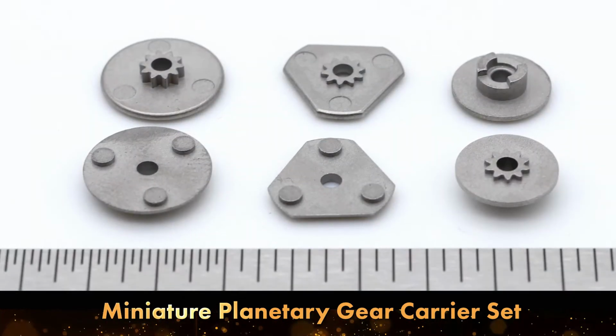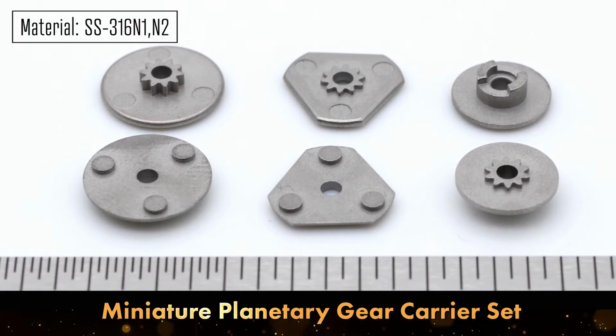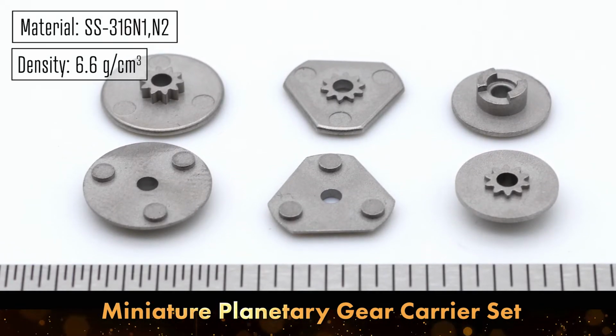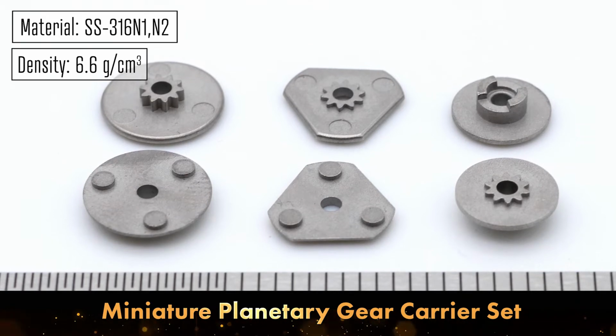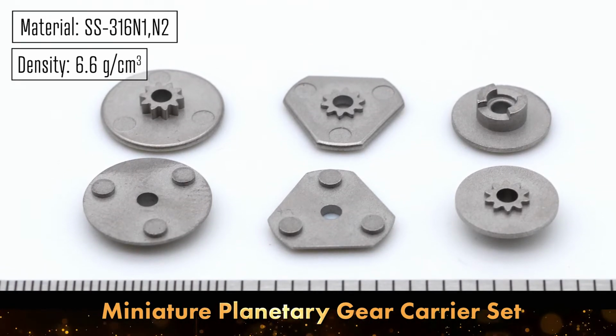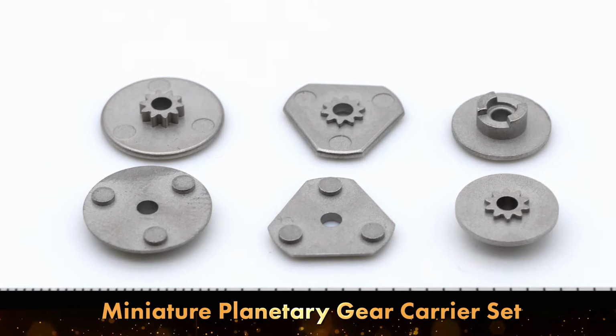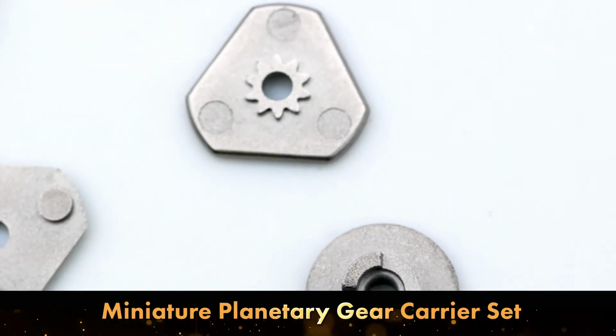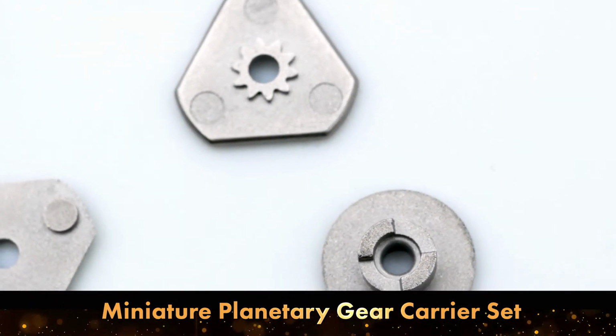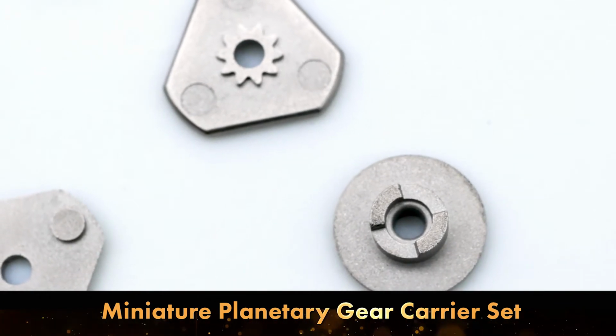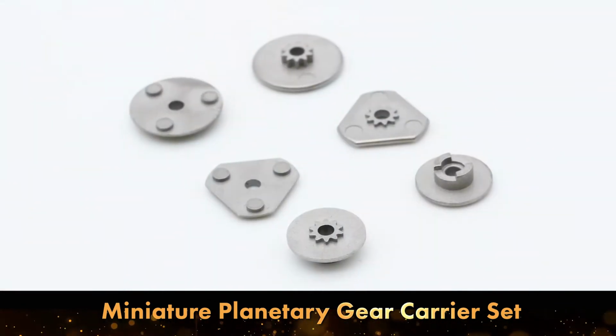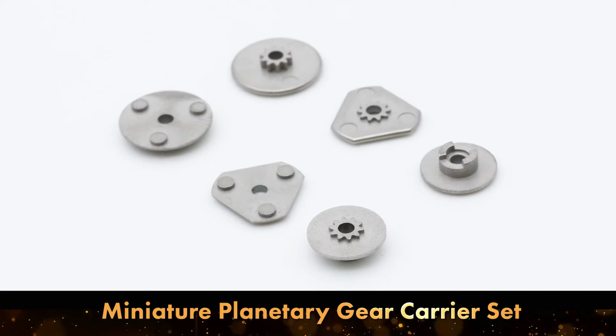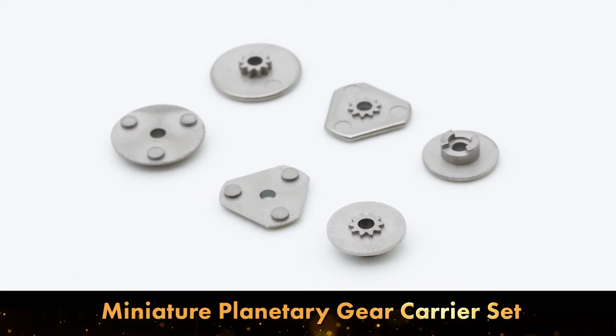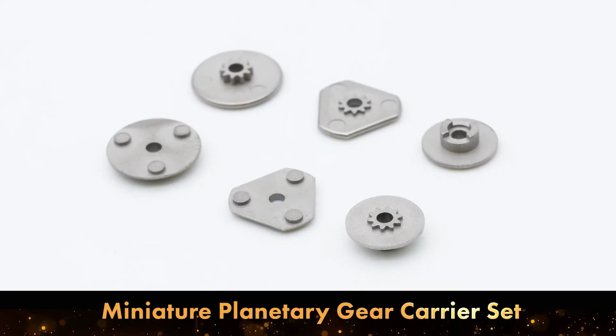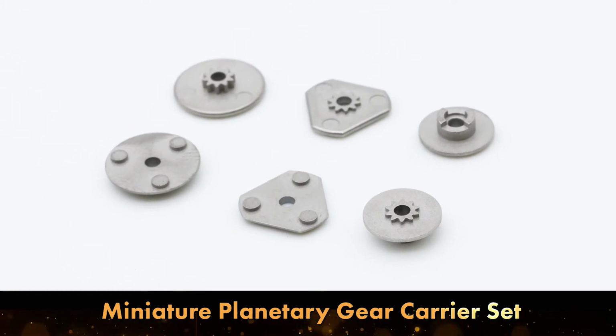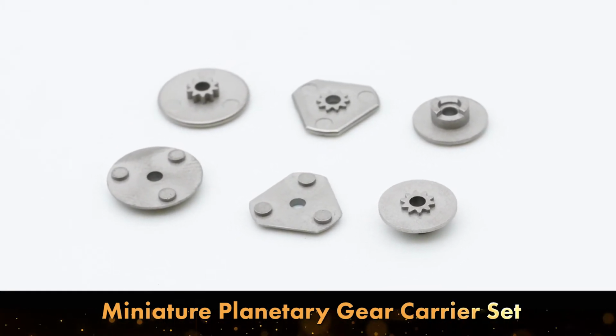The parts are made from 316 N1 N2 stainless steel, compacted to a green density of 6.6 grams per cubic centimeter, and sintered in a hydrogen-nitrogen atmosphere at 2100 degrees Fahrenheit. Each one of the 3 parts has an inside diameter tolerance that is held to plus or minus 1/1000th of an inch, and a thickness held to plus or minus 2/1000ths of an inch without the need for any post-sintering machining. Using conventional PM, this component had a 50% cost savings over metal injection molding.